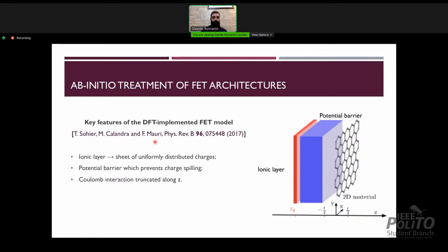Therefore, recently, a model has been implemented in DFT codes, which treat the ionic layer or the metallic gate as a uniform planar distribution of charges. The dielectric is completely removed and a potential barrier is inserted in order to avoid charge spilling from the system into vacuum.